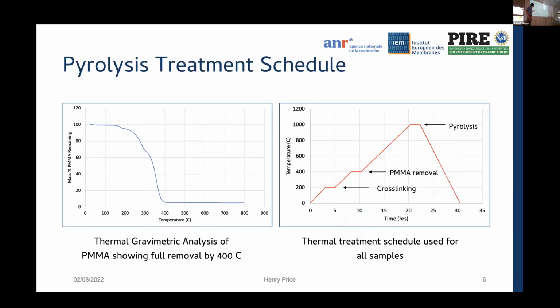So a bit on the pyrolysis. The first thing we did was conduct TGA on the PMMA itself to verify at what temperature it would be completely removed. And this was found, as you can see, to be by 400 degrees Celsius. This value informed the pyrolysis treatment schedule that we used. You can see initially there's a plateau at 200 just to make sure the sample is completely cross-linked. There's another plateau at 400, and this is to ensure that all of the PMMA is removed. And then, of course, at the top, we conducted pyrolysis at 1,000 degrees.